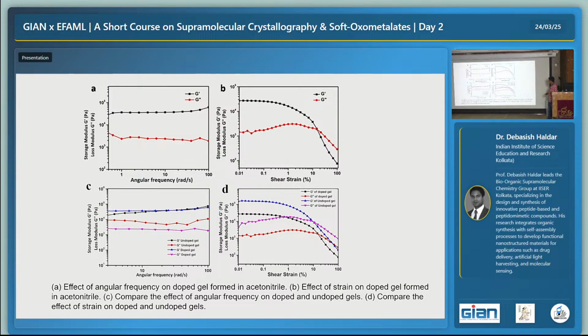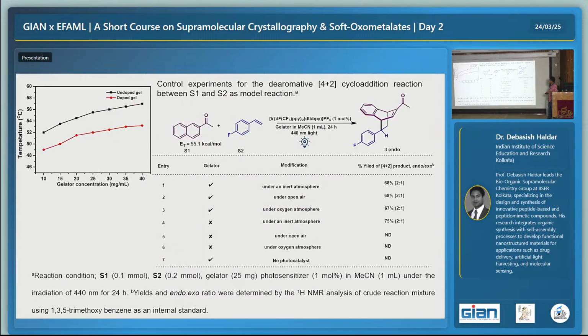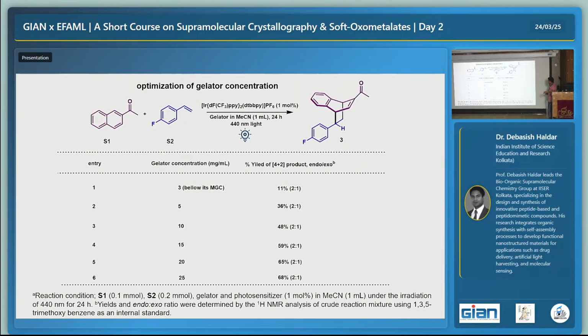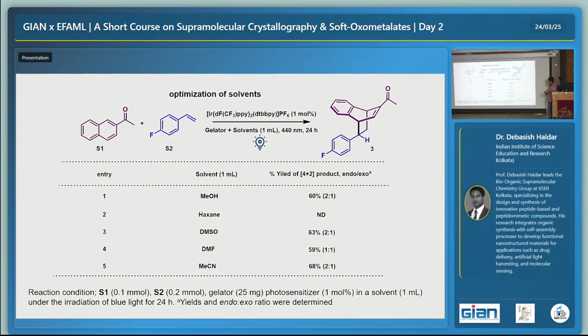the gel is changing. And then we have optimized the concentration of the gelator, and we figured out that at 25 milligram per ml gel concentration, the reaction is happening very nicely. And under open air, we are getting 68% conversion, which is quite good. So we have also optimized the gelator concentration, and what I have said is that at 25 milligram per ml gel concentration, the reaction is happening nicely.